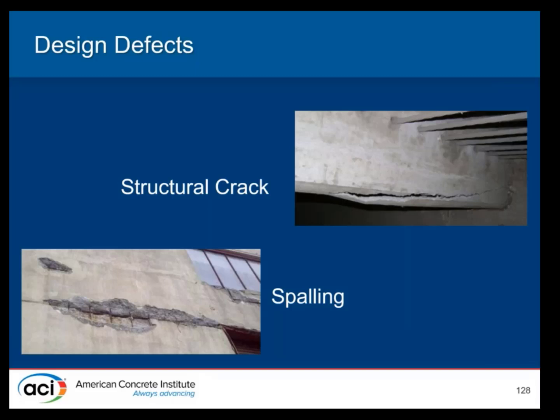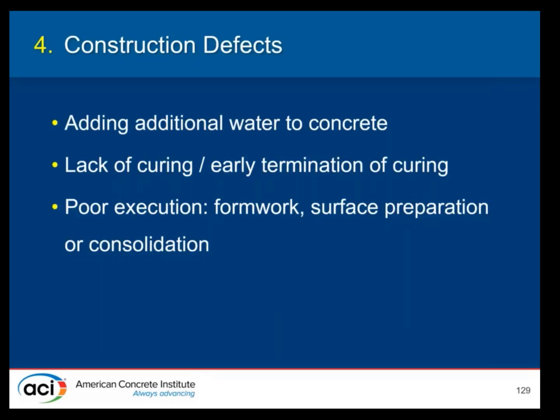And so these steel reinforced members were close to the surface. And as you can see, there's a joint which also helped to collect water. And as that water penetrated into the concrete, the low cover steel was corroded. And that led to spalling of the area in an unsafe condition.